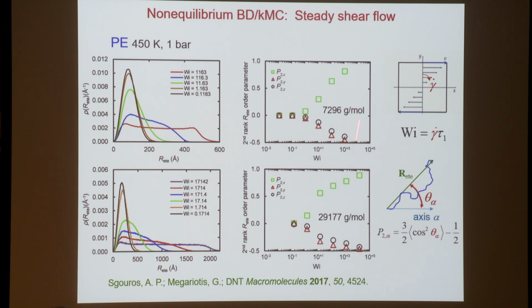Shown here are the orientational tendencies of the chains as a function of Weissenberg number. We have the second Legendre polynomial formed from the angle between the end-to-end vector of a chain and the three coordinate axes, x, y, and z. We see that for weak flows, for Weissenberg smaller than 1, the orientation is random. This P2 is equal to 0. However, when the flow becomes strong, there is a pronounced tendency for the end-to-end vector to orient parallel to the x-axis of the velocity and normal to the y and z axes. In fact, there is a small difference between the y and z axes, which leads to what is called the second normal stress difference for these sheared melts, which is captured quite well by this mesoscopic simulation approach.